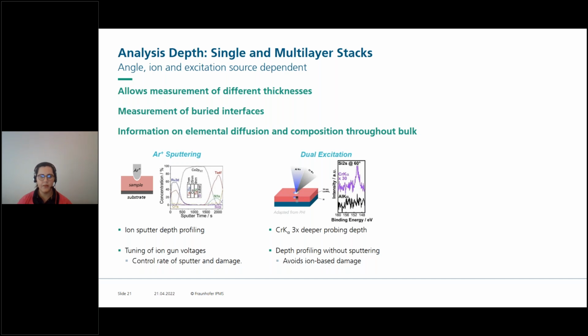Another way we can do analysis depth is with dual excitation. So, for example, normally aluminum Kα can measure up to 10 nanometers in depth, depending on the material and its density. And chromium Kα normally can measure up to 3 times deeper in probing depth.